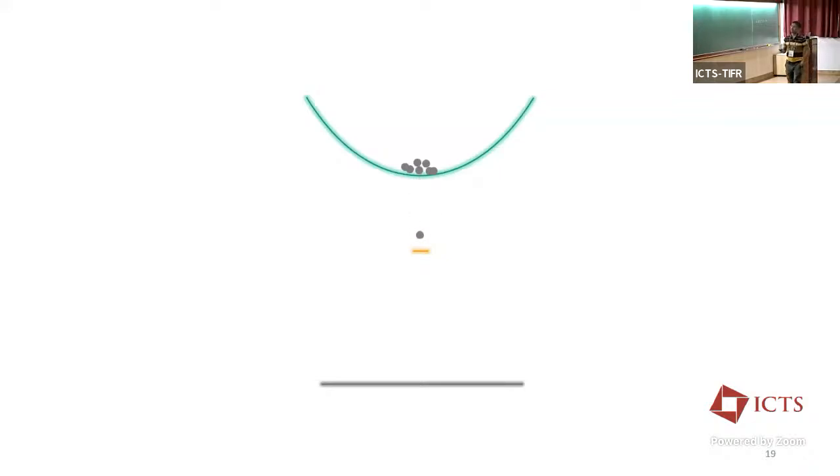And so what happens is that because there are a lot of excitons here, they act like a reservoir, and it kind of falls here, and this is a single state. So that will emit one photon, the next one comes here, that will emit a photon, like that. So that's how, through this bottleneck single level state, you can get one photon at a time. Okay.